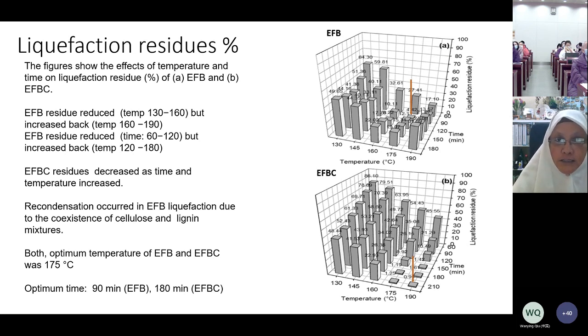So we make two, one using empty fruit bunch, and the other one, the lower part, just using the cellulose without lignin. Without lignin, you will notice that you can have as low as 0.9% left as far as the residue is concerned, because we want as high a yield as possible. And for EFB, you can get about 4% here, which is much higher compared to EFBC.